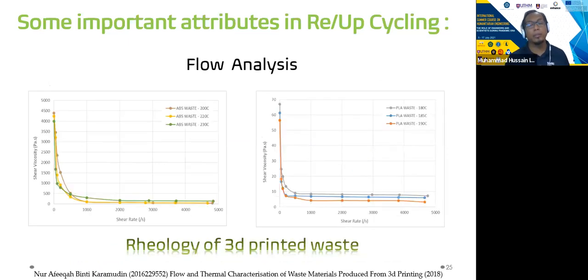Another aspect is the flow analysis. When we apply temperature on this plastic material, the viscosity will change. As the temperature increases, the viscosity decreases as a function of temperature. So this figure shows the correlation between the viscosity as a function of shear rate at various temperatures. For example, this one is the rheology of 3D printed waste. We studied two different types of material that are commonly used in 3D printing.